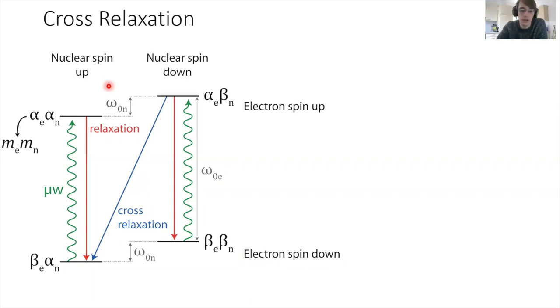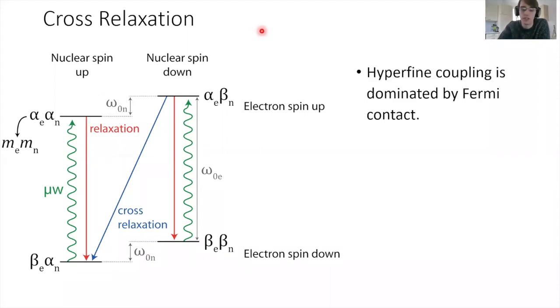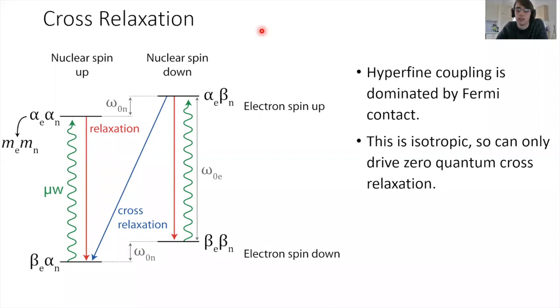Those of you who are maybe more familiar with DNP, or indeed the Overhauser effect, might be asking why I haven't shown double quantum relaxation, which is the one that goes the other way. This is because, as I mentioned earlier, the hyperfine coupling is dominated by Fermi contact, and this is an isotropic interaction, and so it can't drive double quantum. It can only drive zero quantum relaxation. To get double quantum relaxation, you need an orientationally dependent interaction like the dipolar coupling, and this is much weaker. So the zero quantum cross relaxation dominates.